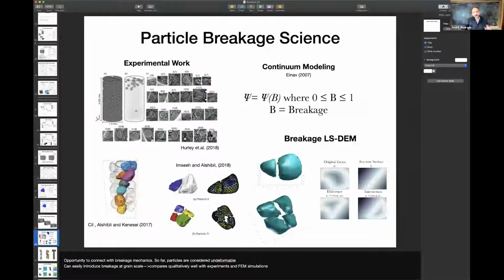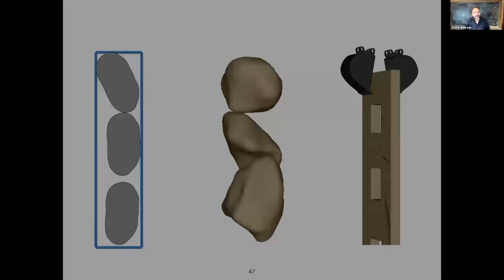And so lots of work happening in this field in particle breakage science, experimental work coming from the Hurley lab. This is a recent paper. Of course, Einav from Sydney doing continuum modeling with this breakage parameter B, right, that goes from 0 to 1 as your breakage evolves. Al-Shibli doing finite elements to break these particles using fracture mechanics, you know, sort of a continuum approach at the particle level. And then our recipe for this problem is to do our level set DEM, but enable it with the ability of splitting these particles.